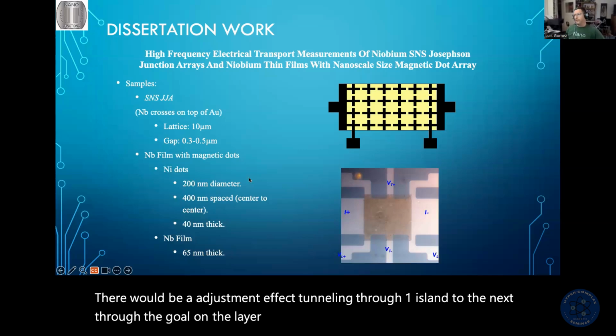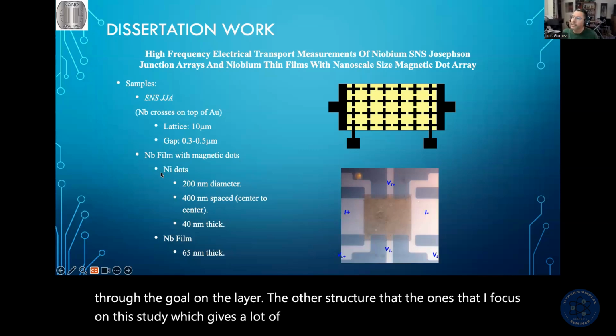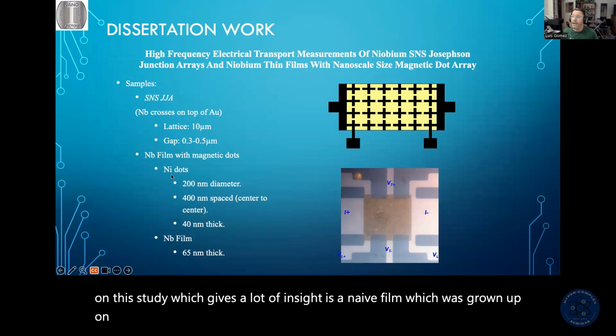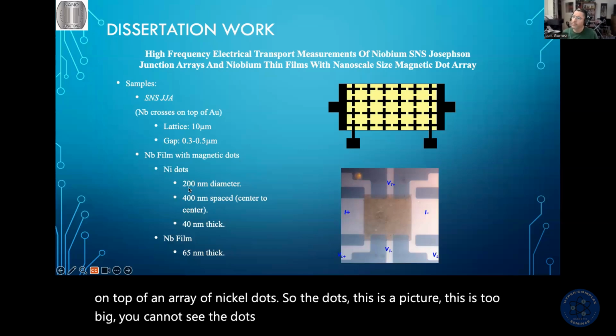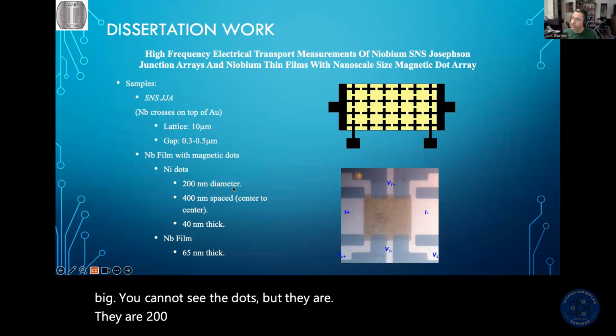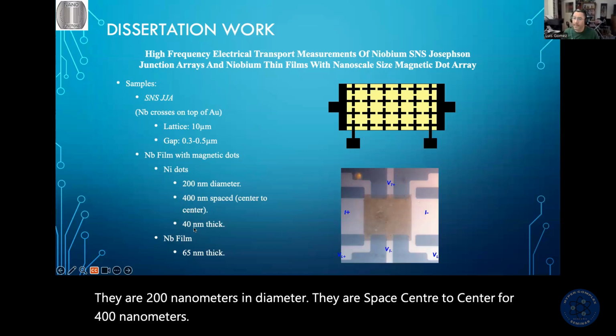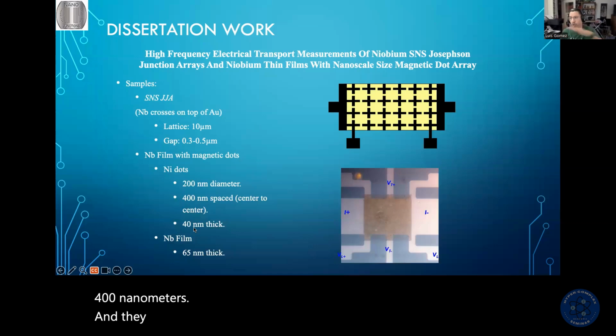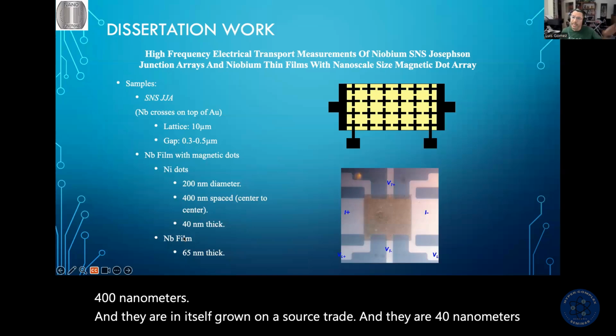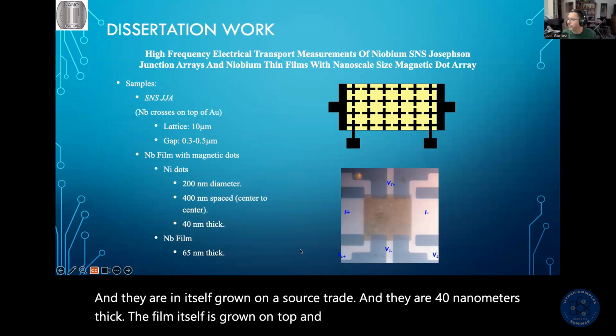The other structure, the one I focused the study on, which gives us a lot of insight, is a niobium film grown on top of an array of nickel dots. This is a picture, but it's too big so you cannot see the dots. They are 200 nanometers in diameter, spaced center to center by 400 nanometers, and are themselves grown on a substrate, 40 nanometers thick. The film itself is grown on top and is 65 nanometers thick.